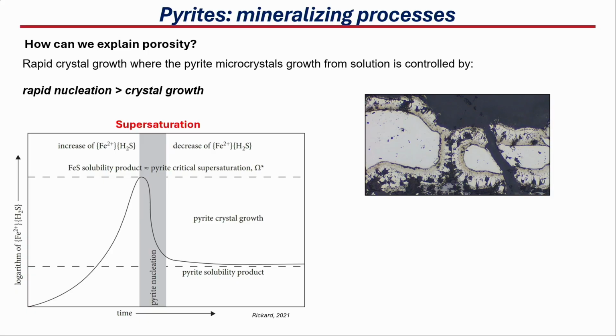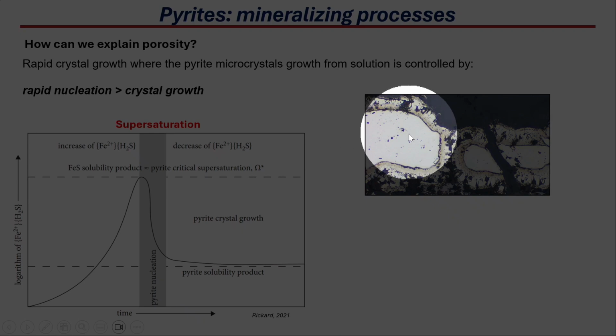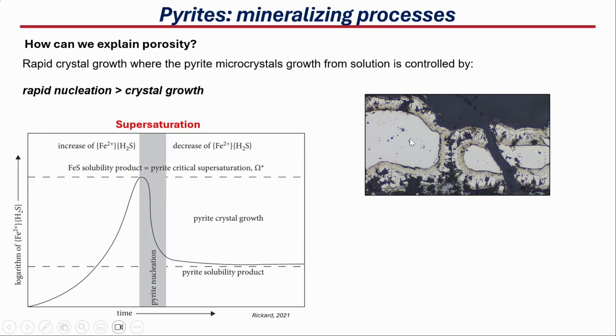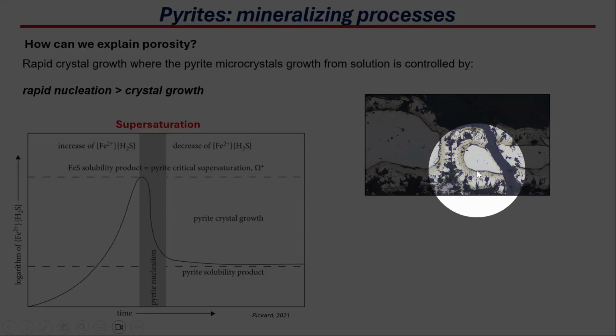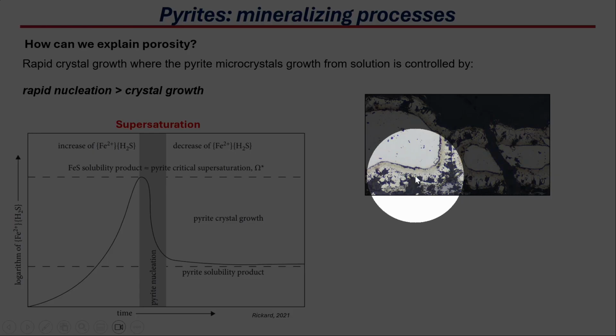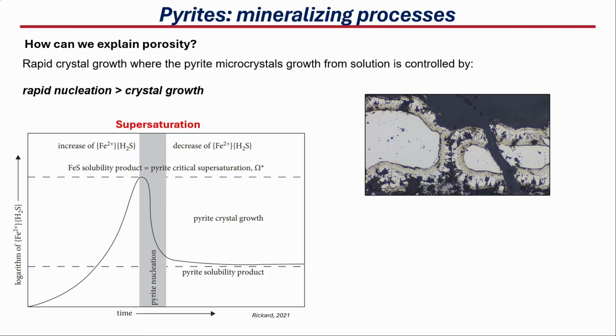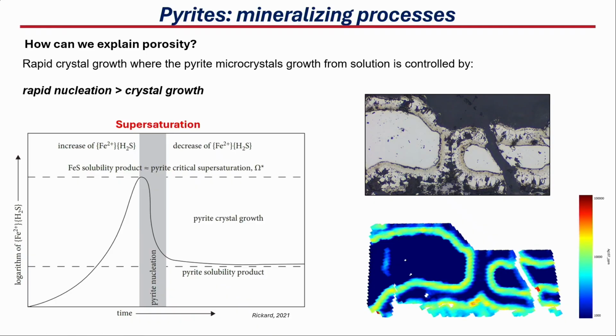petrography. So here there is an image where we have a non-porous pyrite again. We have a very fine rim, which, if you can see, is like a brownish color. That is a very fine-grained porous pyrite. And after that, we see another area with non-porous pyrite, followed by another rim of porous pyrite. So we see a cyclicity in these processes. And in the trace metal distribution, in this case I added silver, what we can see is that we have regions of silver poor, silver rich, silver poor, silver rich, regarding the pyrite type. So we associate this cyclicity with metal-rich fluids, which we think are associated mainly with the hydrothermal breccias.